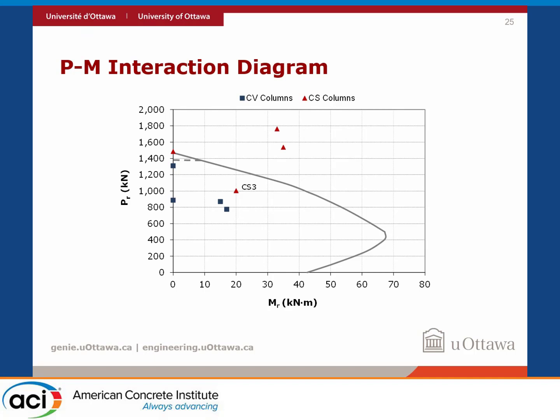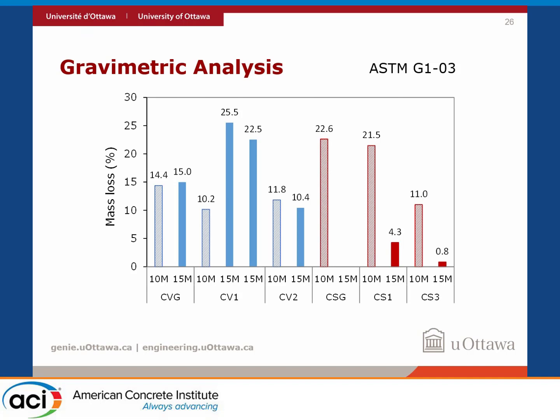After the test, we retrieved some reinforcement samples, and we conducted gravimetric analysis according to ASTM G1, which is basically taking reinforcement samples and subjecting them to a chemical bath to see what the weight is after corrosion products have been removed. And what we see for the first series of columns is that even though only the longitudinal reinforcement was corroded, the spiral reinforcement was corroding as well. We don't know if the electrical connection or isolation that we provided was not good enough, or if it is because the spirals are closer to the outside, and because we were subjecting them to wet and dry cycles and there was already chloride in the concrete, they corroded.